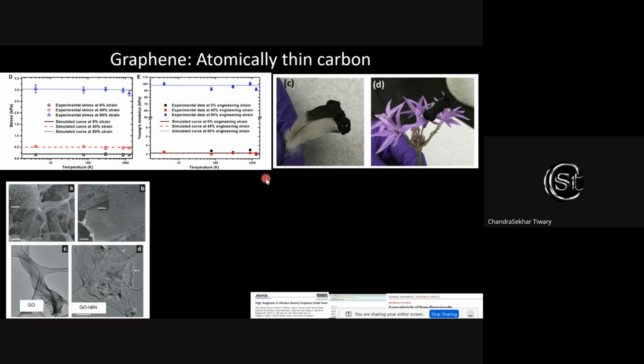Now, if you look at the structure of graphene, another advantage graphene has to offer is that it is atomically thin. So after graphene, you get many more atomically thin materials which can be easily put together with this. For example, hexagonal boron nitride is just physically mixed, or you put it in solution, mix them, and they can nicely stick to each other or stay together. And the simple reason is the surface charge helps them to build the structure.